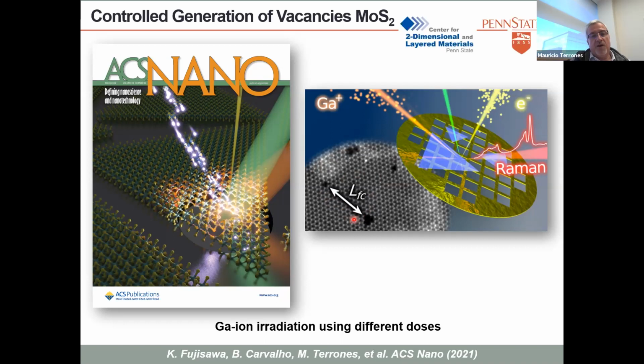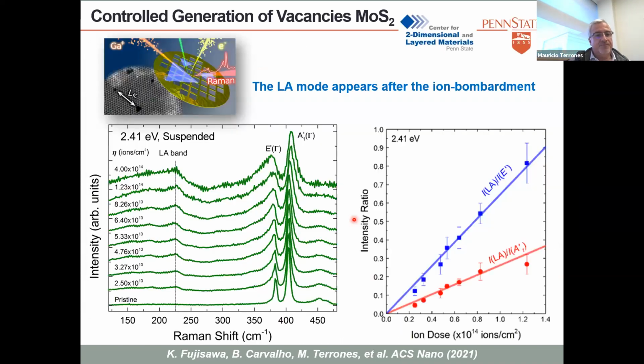So we ended up having a formula that people can use. What we did is we used the pristine material, and we started irradiating with gallium atoms, right? And you see that the LA mode starts appearing as the number of defects increases, and that's similar to the D band in graphene.